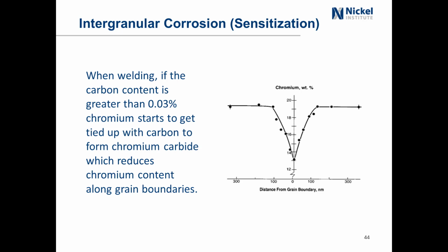But you might only be knocking down the chromium. We could say this is maybe a 304, so we've got like 19% chromium, and in a worst case scenario, the chromium at the grain boundary is down to like 13. It's still a stainless steel. And in a mild environment, say like in milk, you're not going to get corrosion along the grain boundaries with 13% chrome. It's enough. But if you were using it, and we had the example of, say, ketchup, and you had welded a 304 or even a 316 with the higher carbon, you could reduce the corrosion resistance along the grain boundary enough that you could see intergranular corrosion in the heat-affected zone of the weld.